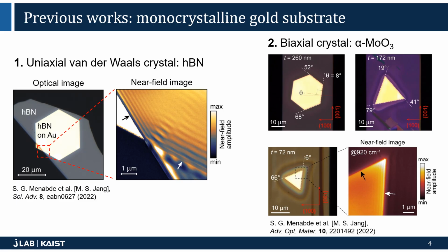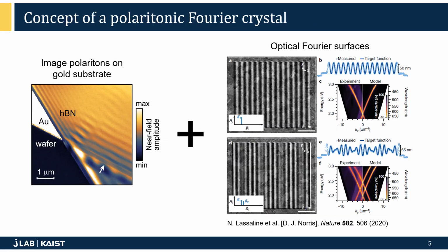Both studies revealed that the lifetime of phonon polaritons screened by gold is similar to the lifetime in suspended material, while their momentum is significantly higher, thus increasing the number of optical oscillations in propagating polaritons. Furthermore, gold is a really good substrate for near-field imaging at mid-infrared frequencies, as it behaves as a lossless mirror. This significantly increases the signal-to-noise ratio in SNOM when polaritonic material is probed on gold substrate.